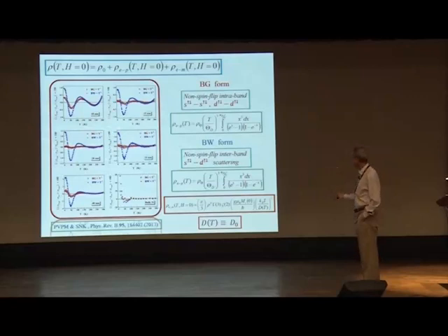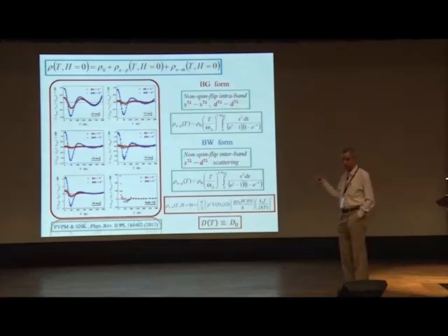That means by introducing the electron-magnon term of T-square form, we are able to reduce these deviations and describe the data better and better. Now, the next step is obviously to include the thermal renormalization of spin wave stiffness, which we have neglected in this case, and then see what happens to the deviations.